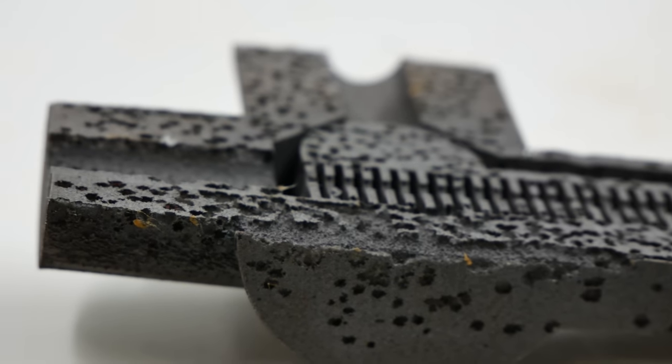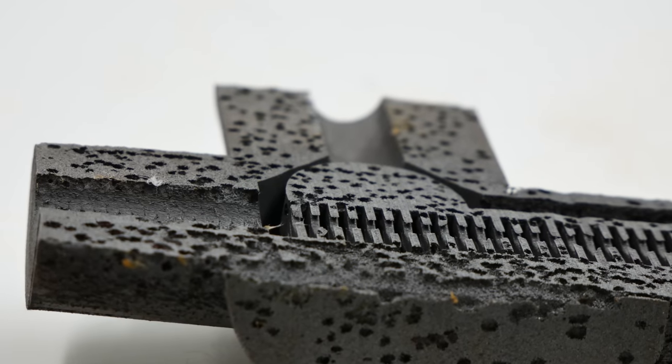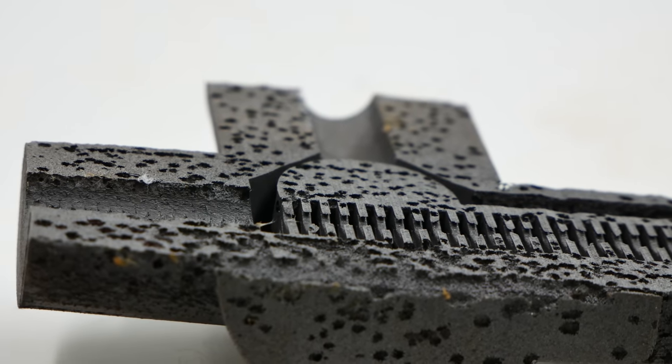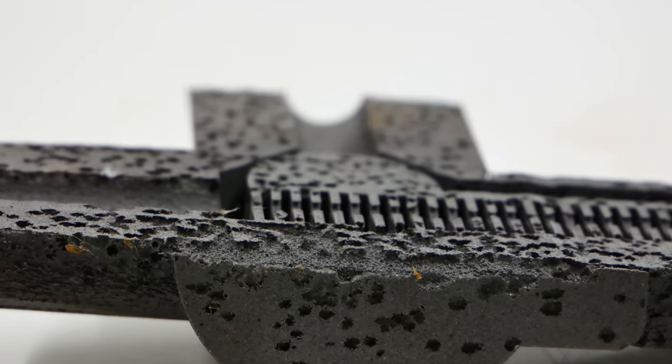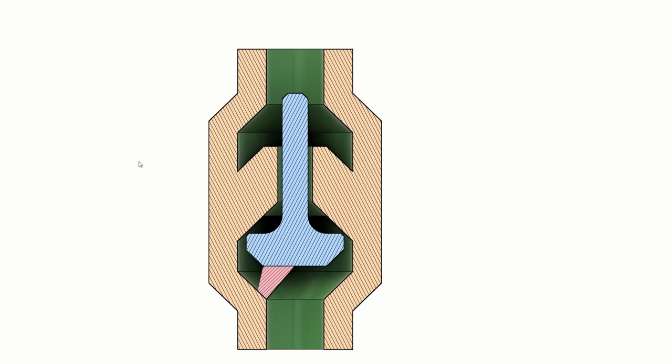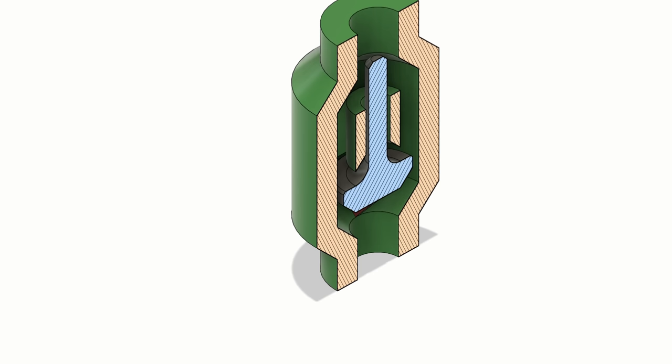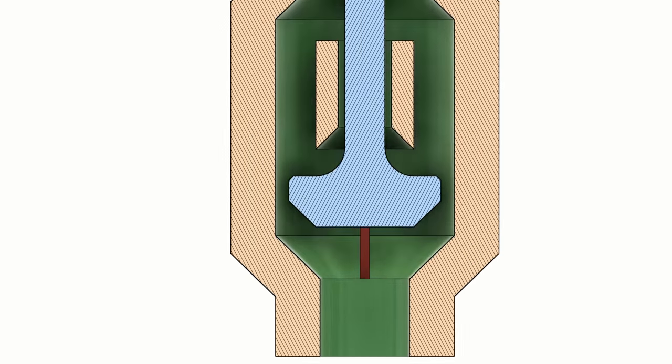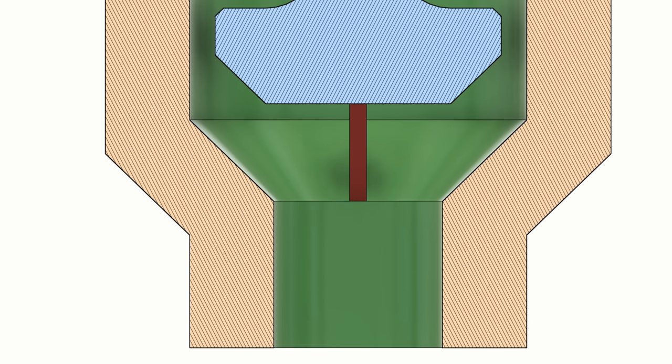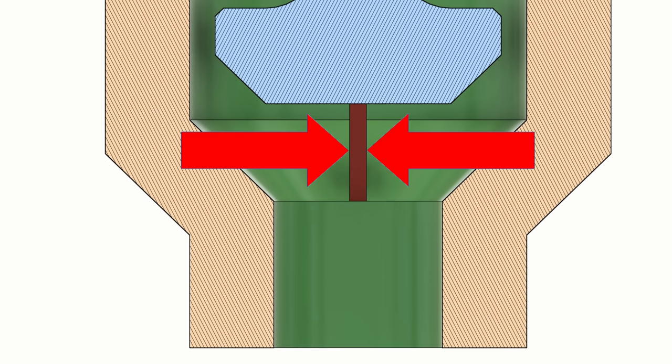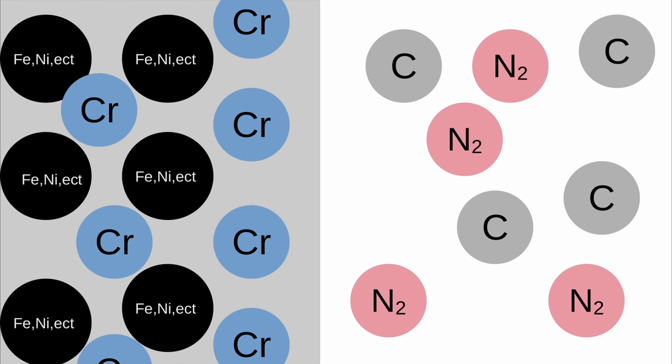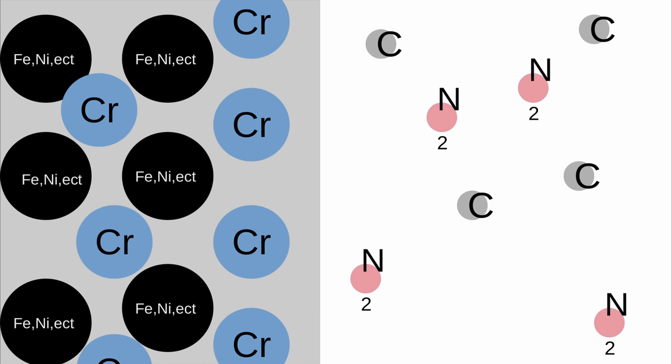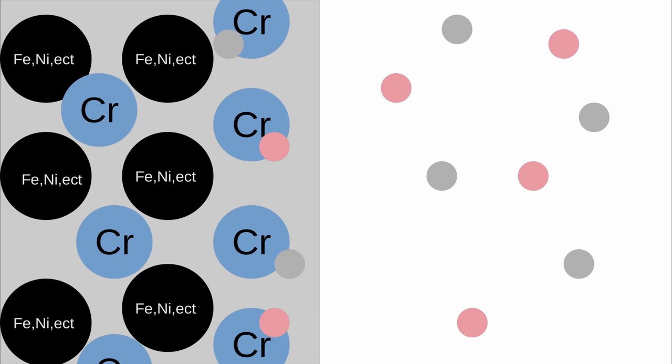We have a way around the problem. Let me show you. We want to be able to remove exactly half the width of a support structure off every single surface in the part. So if our support structures are 0.2 millimeter wide, we want to remove exactly 0.1 millimeter from all the surfaces. This way we can remove the support structures entirely and every other surface we can compensate for in the design. By exposing the stainless steel to a carbon and nitrogen rich environment where the carbon and nitrogen are actually really small particles, under high temperature these are able to sneak in or diffuse into the steel.